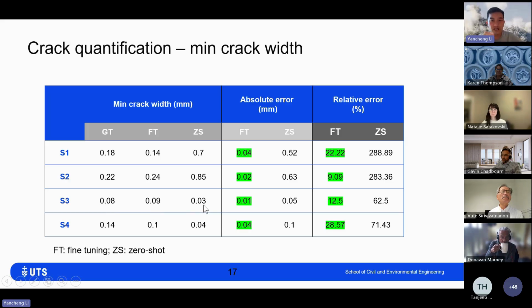This means the algorithm with zero shot wasn't able to correctly define the cracked pixels in the image. But with fine-tuning, we are able to really reduce the error, from very high, nearly 300%, to 20%, to nearly 10%. It's a very good result in terms of minimum crack width. A very important parameter is 0.1, as mentioned by Karen. We are able to detect this very fine crack with our algorithms.